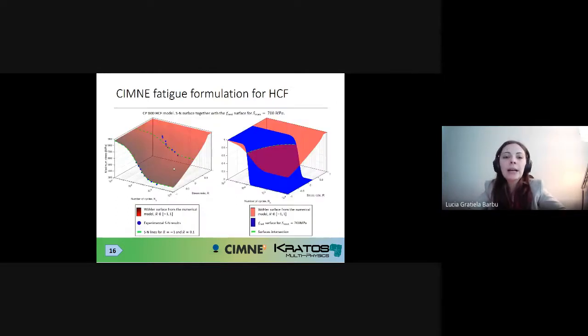And just to finish this part, I want to stress that we are not working with discrete, isolated SN curves. When we are calibrating these materials and we are calibrating specific curves for specific reversion factors to experimental points, what we are actually doing is we are configuring this whole surface of the SN curve. So for instance, if in a numerical simulation, in a finite element simulation, you start to have damage due to fatigue, what will happen is that you will have right away a stress redistribution outside of the area where you have damage.